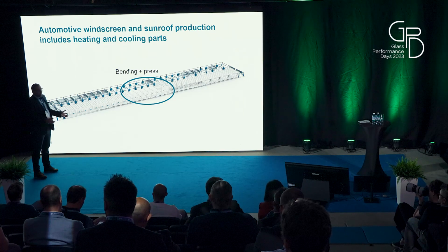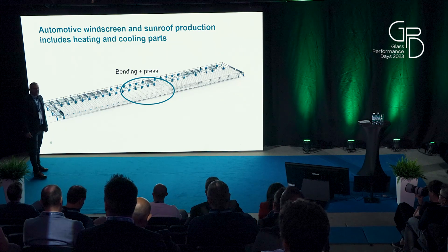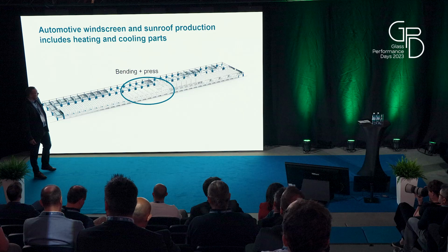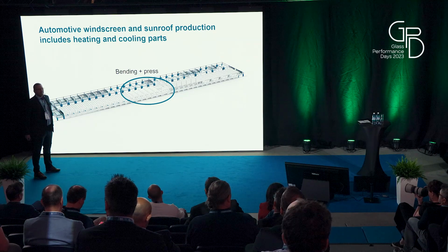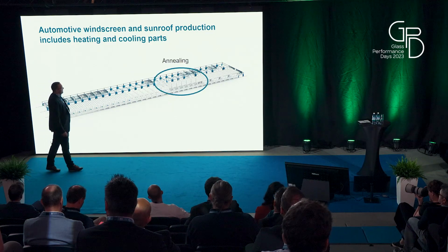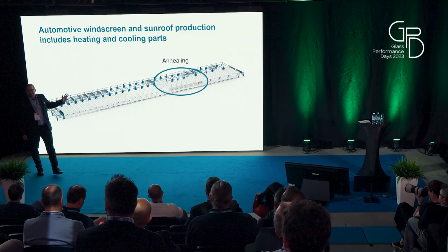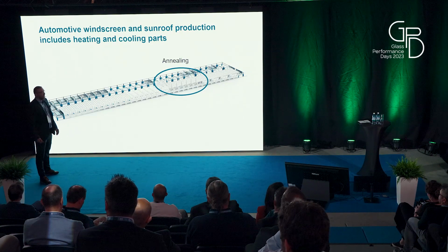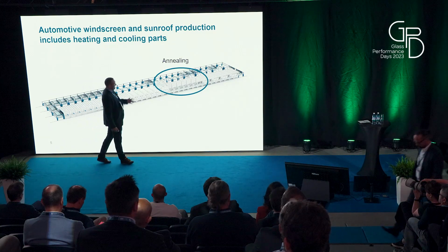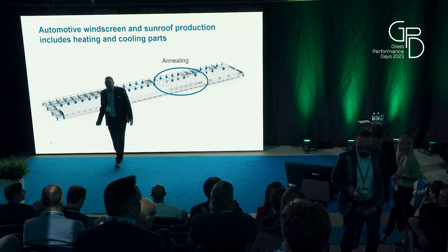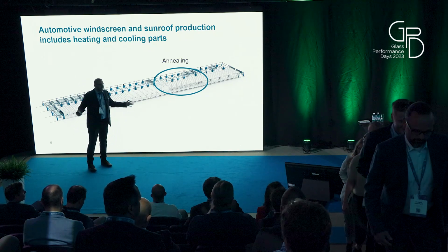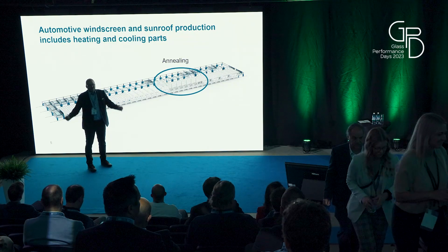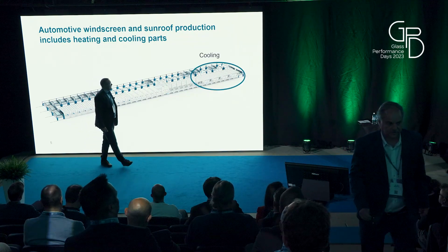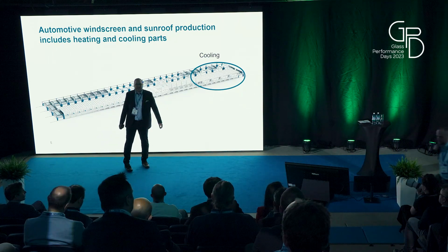So when the glass is around 500 degrees, glass is still staying flat. It doesn't bend that much. But when we go to the bending part and the pressing part, glass is heated to around 620 degrees, and then the bending is faster, and we can get the right shape in the windscreen. After glass is heated and bent, glass goes to the annealing part, where the cooling is controlled so that we can get the right stresses in the glass, so that we can avoid unwanted breakages, say during the process or in use. And at the end, the normal cooling part, so that we can handle the glass.